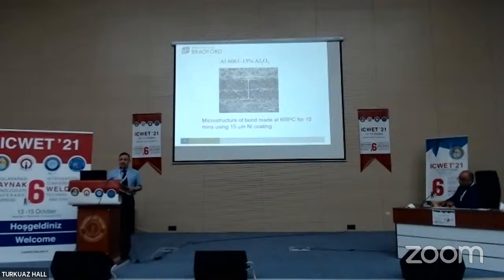Another example is if you try to use TLP, transient liquid phase bonding, to join a composite material, an aluminium composite. Now, aluminium composite is a great material, fantastic properties, but we cannot use it in a proper way. We cannot use adhesives or rivets. And how can we maximize the use of the strengthening particles? So if we use transient liquid phase bonding, this is what happens. We get a region of reinforcement that forms at the joint. So this is the original interface, and the interlayer melts, and then when it solidifies, it pushes the particles. And again, this is a non-uniformity in mechanical properties.